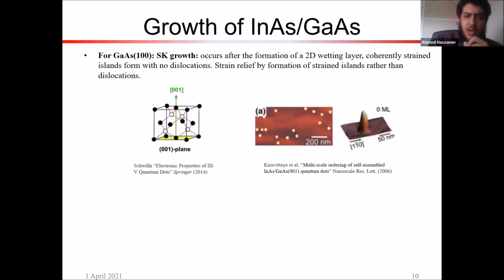And so if we look at the growth of indium arsenide on gallium arsenide, this is the material system we want to use, we see that for gallium arsenide 100 orientation, as we can see here, this is the zinc blende structure, you can see here the 100 orientation. You can see that the growth occurs naturally in this SK growth mode. So we get a wetting layer, then we get strain relief in the form of quantum dots, so we get the wetting layer plus quantum dots. This is an AFM, atomic force microscopy, image of quantum dots on gallium arsenide 100.